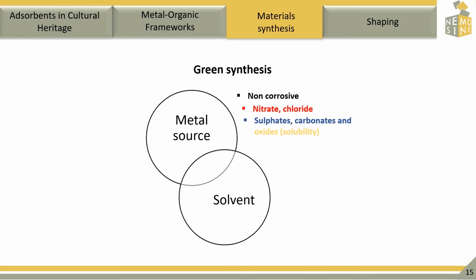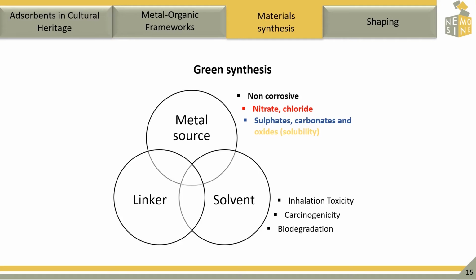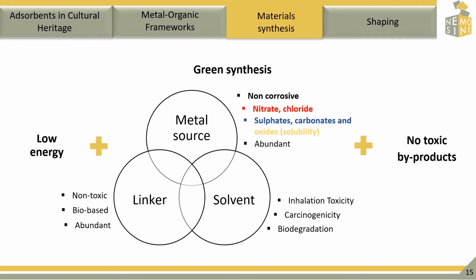So usually also the solvents need to be carefully considered. In MOFs, the synthesis was previously done for a large majority with solvents that present a low health score, meaning that they can be toxic, carcinogenic, or have other health-related consequences. Furthermore, there are other properties of the solvents that can influence their greenness, such as the biodegradability, or if they are not biodegradable. And this can imply that we need further treatments in the downstream, which will also increase the price of the process. The linker considered is also a source of toxicity, so we need to choose a ligand that is not toxic, and it's also beneficial if it is bio-based, meaning that it can have a lower price. In addition, for both the linker and the metal source, it is beneficial if they are abundant. Finally, the process should also require low energy and not form any toxic byproducts, avoiding costly effluent pretreatments.